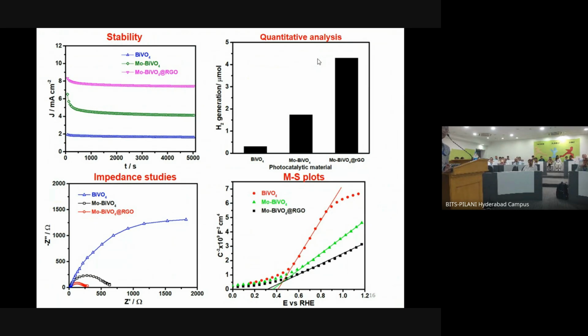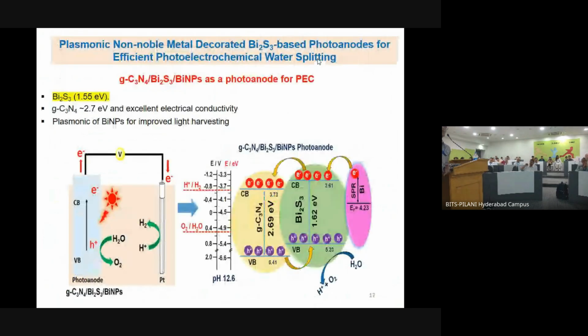And the most important thing: the moment you put in some kind of doping, and you look at these individual combinations, the resistance offered by these materials has significantly come down. Now you see that the RCT value, or the charge transfer resistance, is very small. But as I mentioned, the title says that it's a non-noble metal.